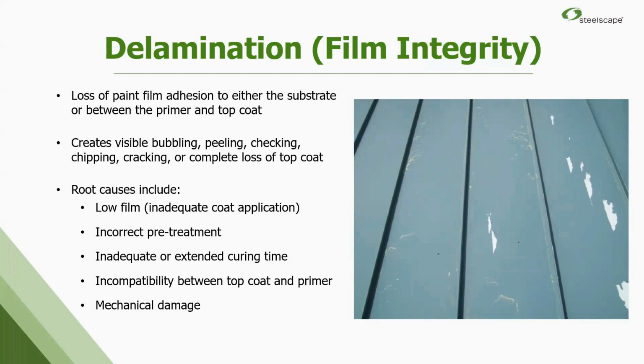But the one we probably see the most is mechanical damage. And by mechanical damage, we mean during installation, something scratched or damaged these painted panels. There's now an opening in the coating where water, moisture, other things can get in there and cause that paint system to kind of come apart. So if you look here on all of these, there's a distinct vertical line where this peeling is peeling away from on every single one.